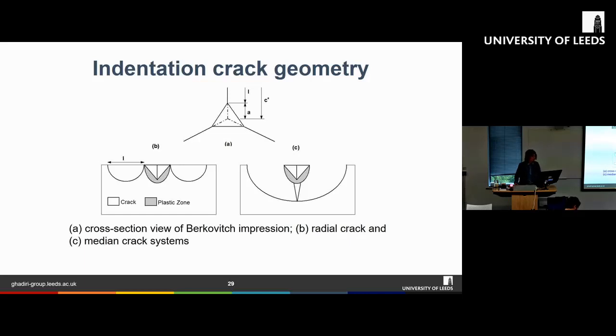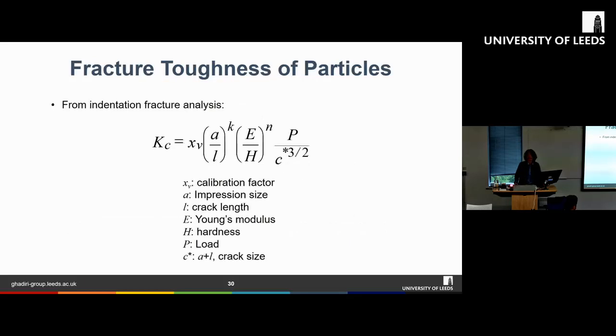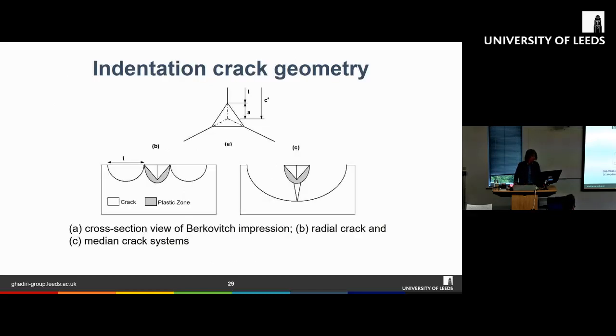By using this measurement of the crack length, we can then easily calculate the fracture toughness of a particle given by this equation here. Essentially, fracture toughness K_c is a function of the impression size, the crack length, the Young's modulus, hardness, load, and C star, which is the crack size, A plus L, as you can see from the previous slide, which is this length we're using.